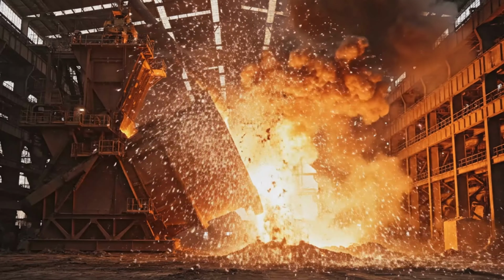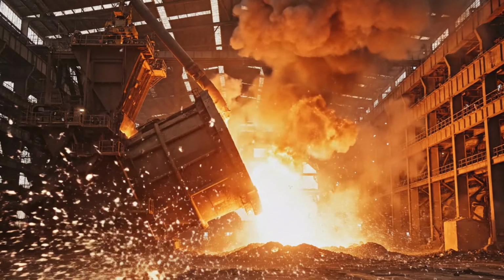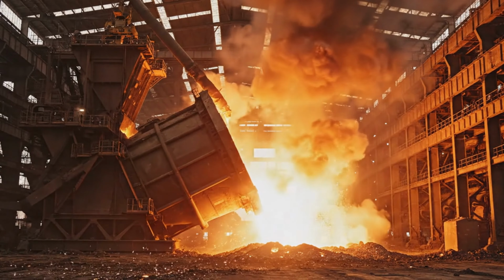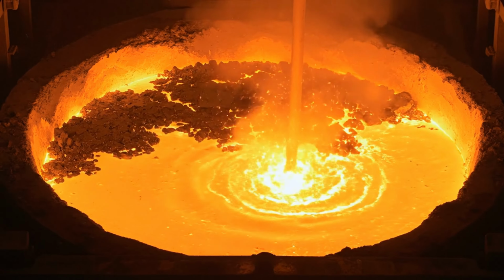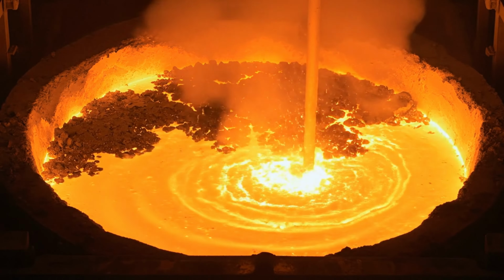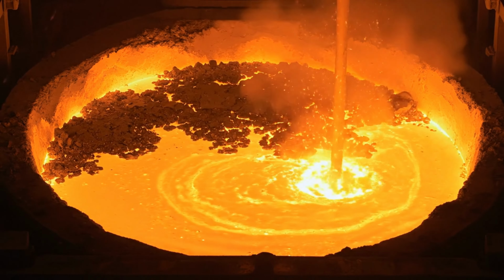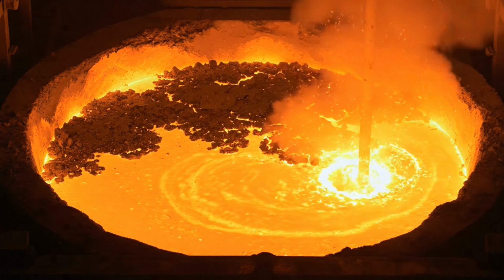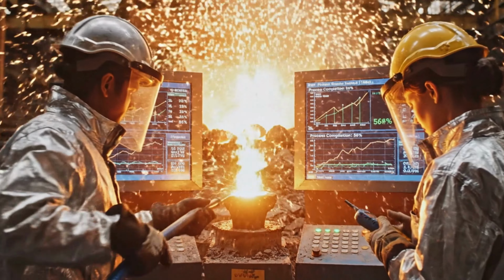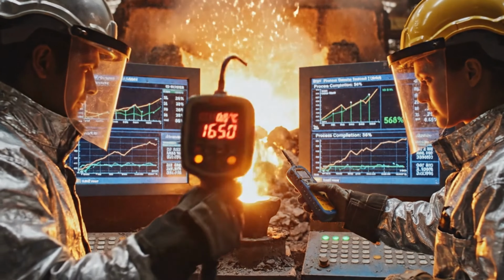Pure oxygen burns out excess carbon and other unwanted elements in minutes. Argon stirring blends the steel and helps clean it from within. Mid-blow checks tell the operators when the chemistry is approaching the target steel grade.